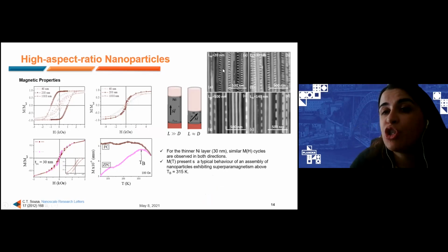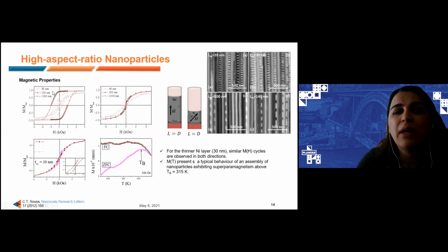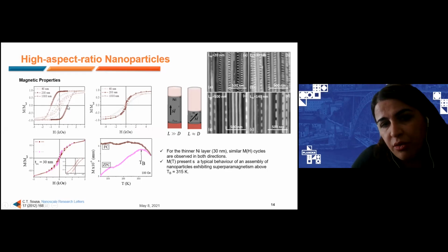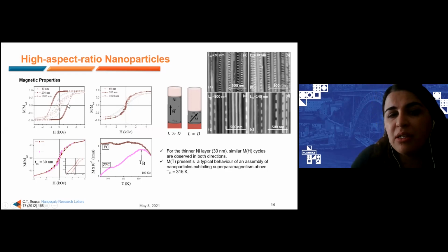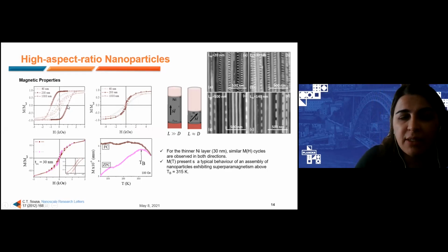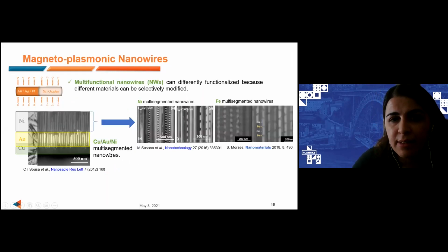We can change the dimensions of our nanostructures from nanodiscs, as you can see here, to nanowires with a high aspect ratio. So by playing with the dimensions of these nanostructures, we can also tune the magnetic properties. We can go from high aspect ratio nanostructures, where the magnetization is mainly dominated by the shape anisotropy, to isotropic nanodiscs, or even for small nanostructures, we can achieve the superparamagnetic state.